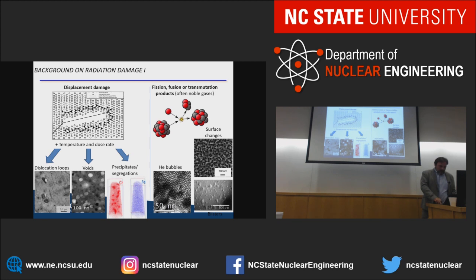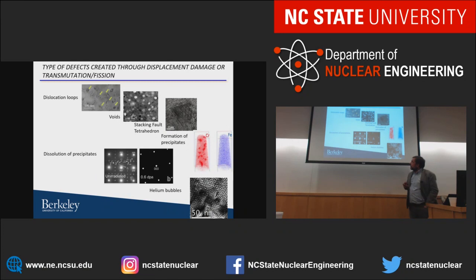So when we look at the subsequent damage this causes, we find that radiation damage causes dislocation loops, voids, stacking fault tetrahedra, formation of precipitates, maybe grain boundary elemental changes. But also we can dissolve precipitates, gamma prime and gamma double prime, which is a nickel-based alloy feature, goes away. So you're losing strength rather than winning, or you form helium bubbles. Now the way I structure these defects is into defects which can be dissolved due to mechanical interaction. So you deform it and your defects go away, and you deform it and your defects don't go away.